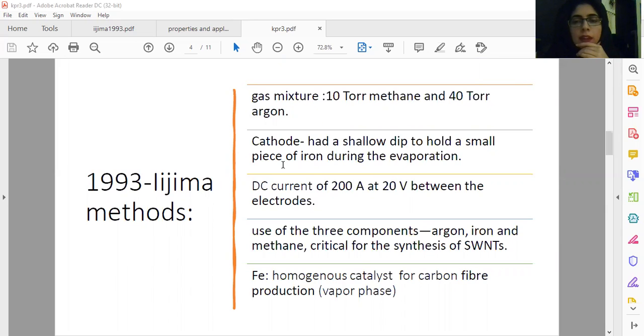Iijima used an arc discharge chamber, which was filled with a gas mixture of 10 torr methane and 40 torr argon. Then they had two vertical thin electrodes, which were installed in the center of the chamber. The cathode, namely the lower electrode, had a shallow dip to hold a small piece of iron during the evaporation. The arc discharge was generated by operating a DC current of 200 amperes at 20 volts between the electrodes. All three of the components, iron, methane, and argon, were extremely critical for the synthesis of these nanotubes. Iron is a catalyst which has been described for carbon fiber production.